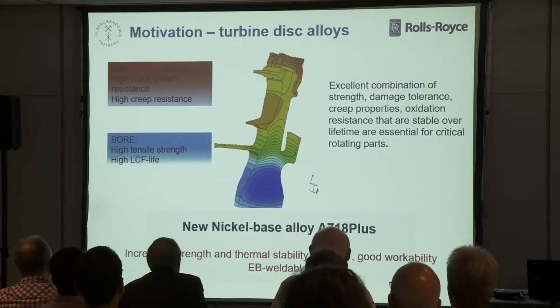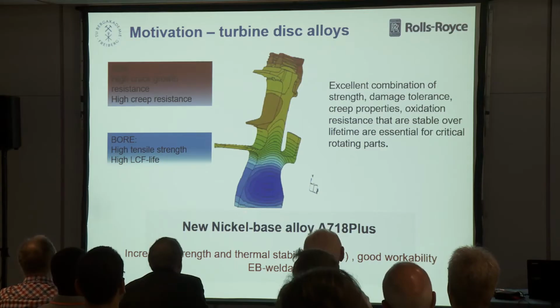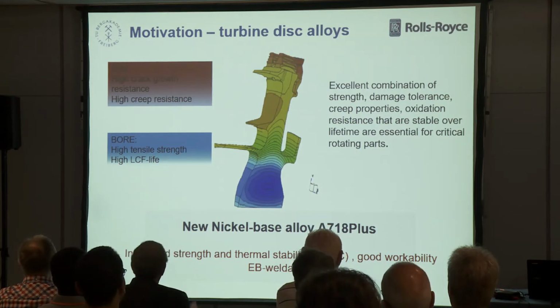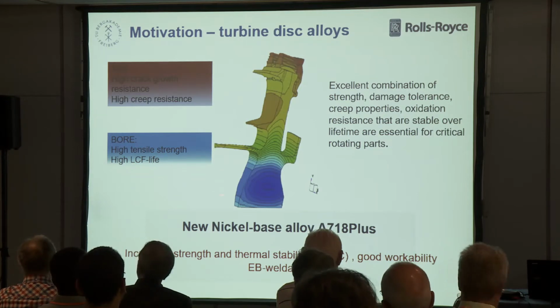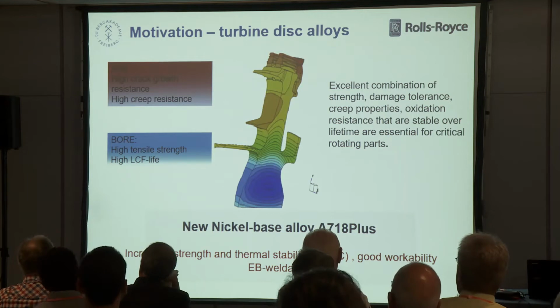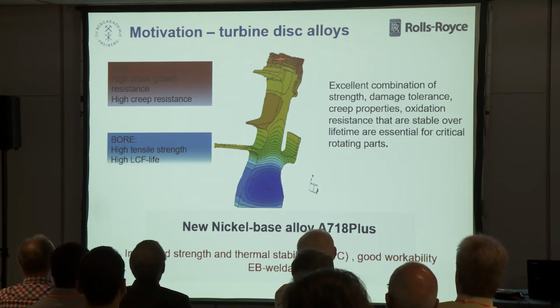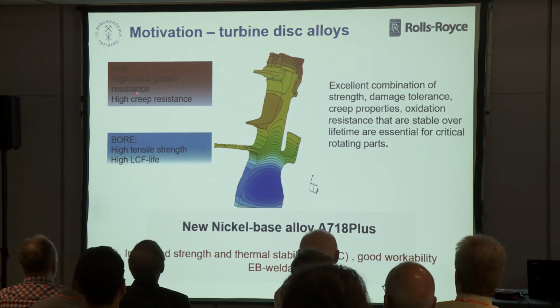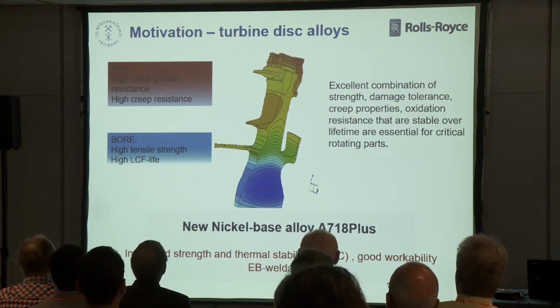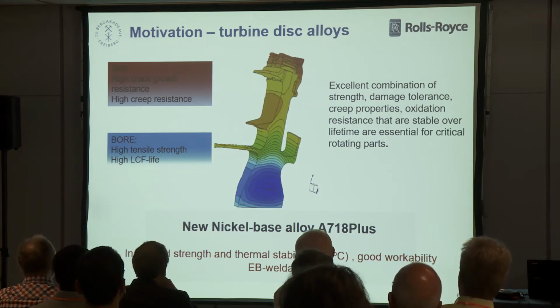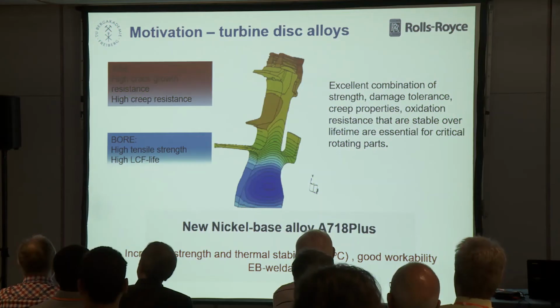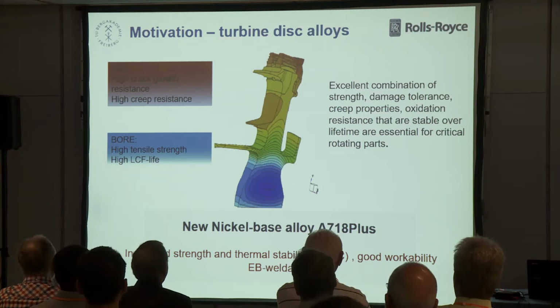So if you look at the loading for such a disc, this is a segment of such a disc. Due to centrifugal forces, here at the borehole, it has to withstand high tensile stress, and of course there is thermomechanical and mechanical cycling, so it needs high low cycle fatigue resistance. Contrary, here at the top, where the blades are attached, we have very high temperature, and we need high creep resistance. So these materials have to have very good properties, a combination of high strength, damage tolerance, creep, and oxidation resistance for these rotating parts.